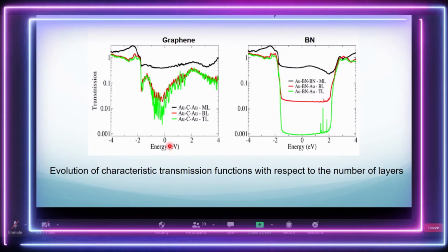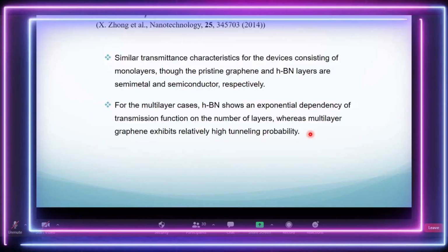Switch now to boron nitride, and you can see here the monolayer definitely is going to transmit electrons. Bilayer a little less, and in the trilayer case, it mimics the intrinsic property of the material, which is semiconducting. So the message that comes out is, at the monolayer level, graphene is a semi-metal or zero gap material, and boron nitride is a semiconductor, yet they have similar transmittance or IV characteristics. But as we increase the thickness, boron nitride again shows it is semiconducting, and graphene shows it is a zero gap material.